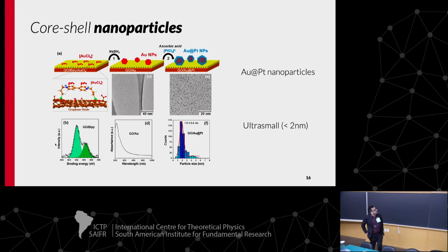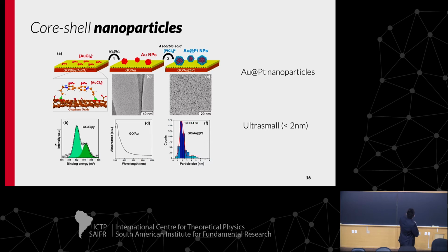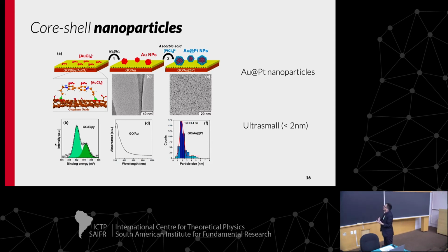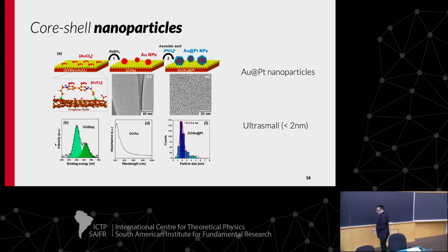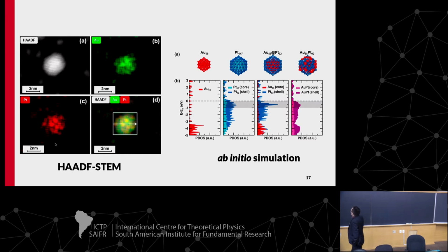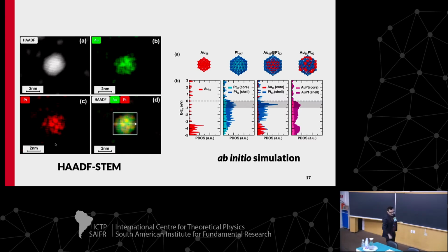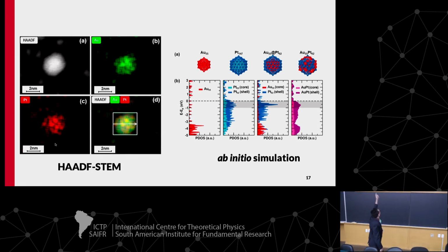At Mackenzie, where I work, we did a collaboration with experimentalists, and they synthesized different nanoparticles. In this case, gold-platinum core-shell nanoparticles, with a gold core and a platinum shell. They synthesized very small particles, smaller than 2 nanometers, using chemical methods on a graphene oxide substrate. In the microscopy we can see a lot of very small nanoparticles. This image was made at LNNano in Campinas. You can see atomic lines, and the patterns of these lines in the nanoparticle.